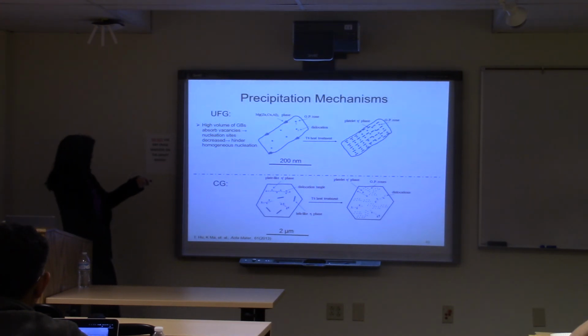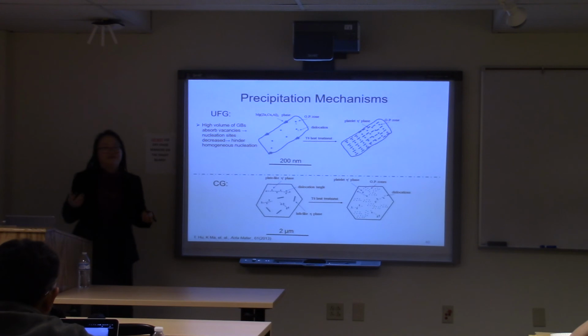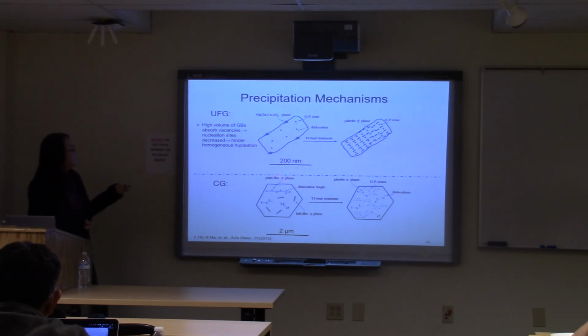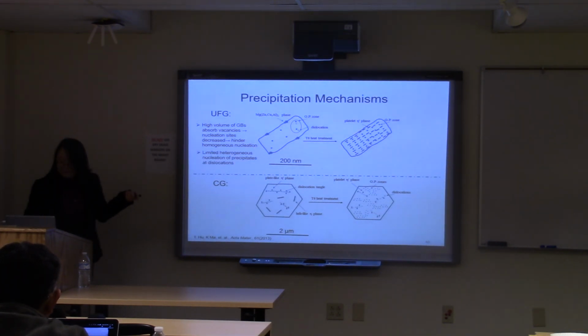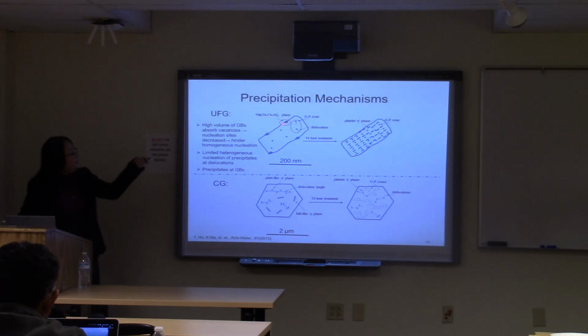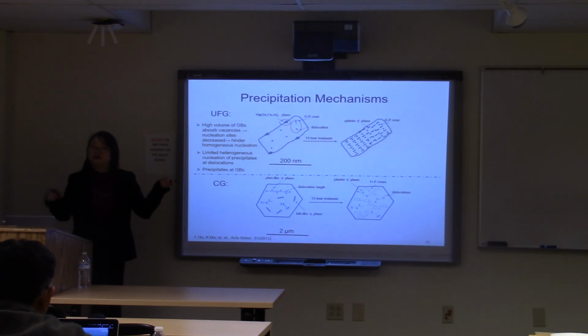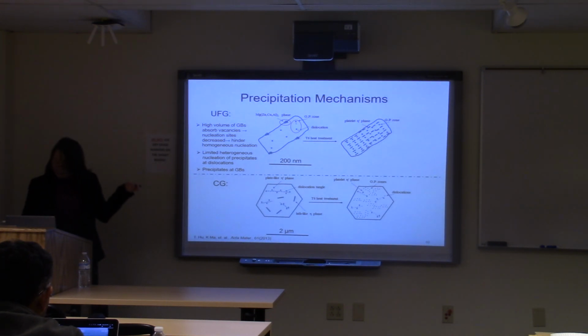Because we have such a high volume of grain boundaries, which is a very good sink for vacancies and dislocations during the thermomechanical processing, they decrease the nucleation sites for the precipitates and hinder the homogeneous nucleation inside the grain. So that's why in the microstructure, which I skipped, we do see very limited heterogeneous nucleation of precipitates at dislocations in that material. And because of the grain boundaries, we have segregation of magnesium and zinc to those grain boundaries. So we find some coarser zinc and copper intermetallics at those grain boundaries.